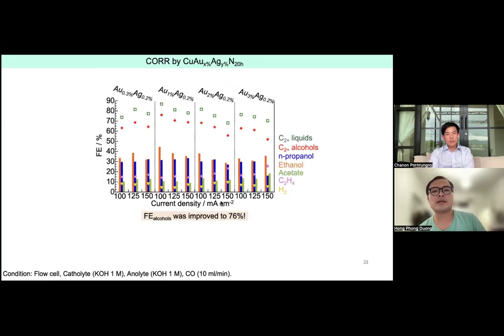But then, if we combine them together and vary the content of the metals, we could boost the alcohol production rate up to like 76%, as shown here. This condition was optimized as 1% gold and 0.2 atomic percent of silver. So this took a lot of time and work to select the ratio and for activity measurement as well. So then we decided to stick with this sample to do further characterizations and activity optimization.